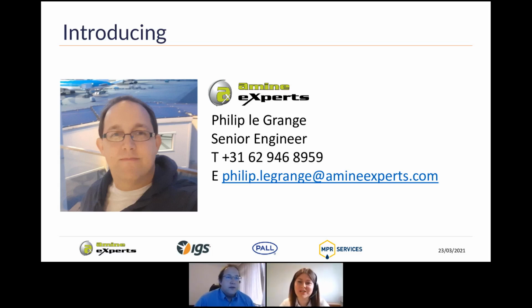Our next question is from Ali. Why do we have HSAS and how can we reduce this? So I won't take too much of Shark's thunder. He's going to be doing a talk fully focused on this topic, but heat stable salts occur because you get something acidic into the system, so you've got oxygen going into the system or hydrogen cyanide. If that enters the system, it'll form a heat stable salt. And because it's a fairly strong acid, you're not going to be able to get it out of the system, so it just accumulates. So even if you have a small amount of, say, oxygen in your feed gas, you can build up a fairly high level of heat stable salts fairly quickly.